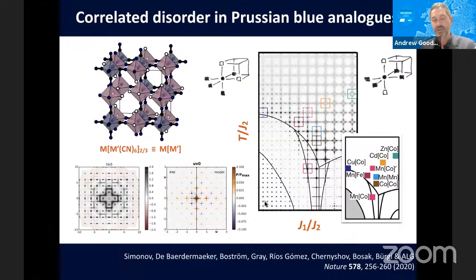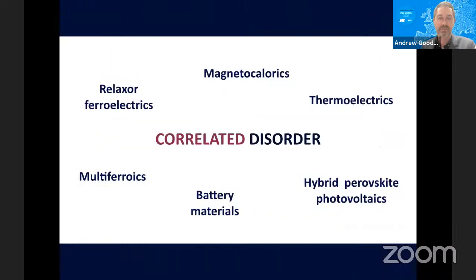And just to finish, the really nice thing from our chemical perspective is that what we're finding is by tuning the chemistry of these materials, we navigate meaningfully different disordered phases. And this is really our long-term goal, to work out how we control the type of disorder within functional materials, where we're optimizing the properties by manipulating the disorder that exists within them. And that's the kind of take-home message we got from these sorts of systems.